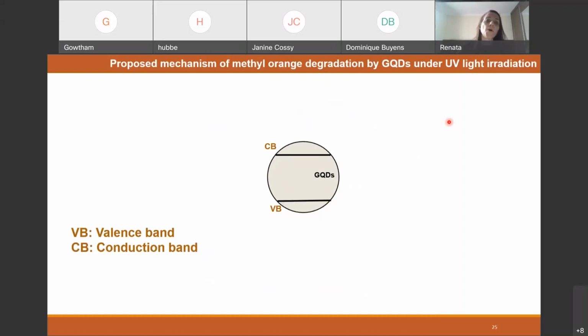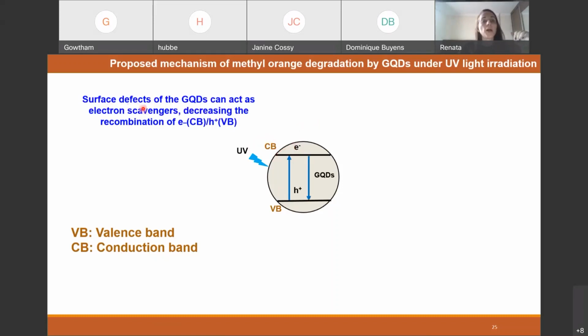Then we propose a mechanism of methyl orange degradation by graphene quantum dots under UV-Vis light. This figure represents our graphene quantum dots. These represent the valence band, and this one represents the conduction band. In the presence of light, the electrons move from the valence band to the conduction band, and it is interesting to say that surface defects of graphene quantum dots can act as electron scavengers, decreasing the recombination of electron-hole pairs. This occurs because of the heteroatoms present on the surface of the nanomaterials.